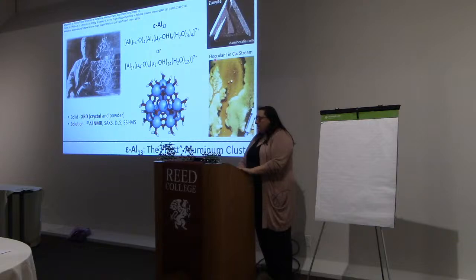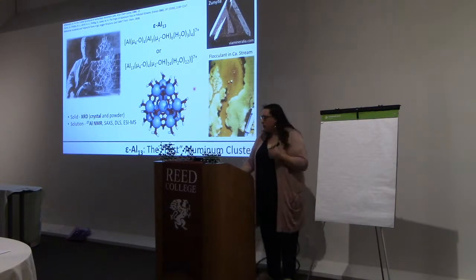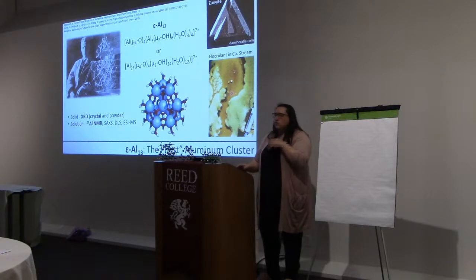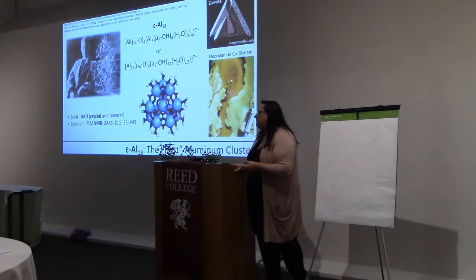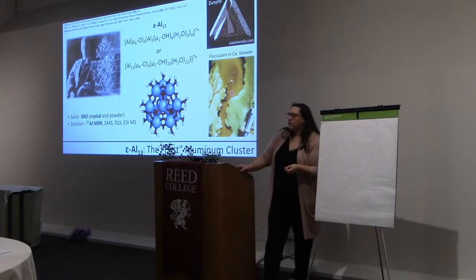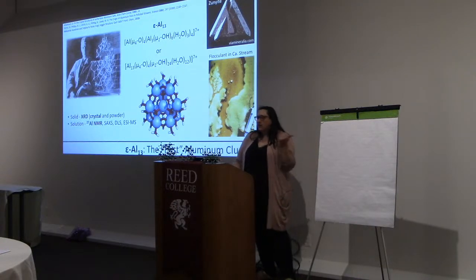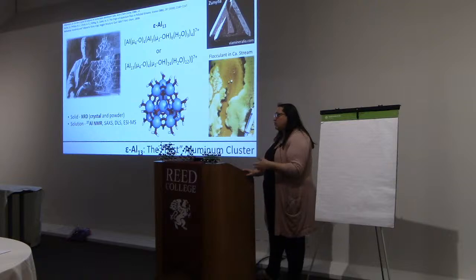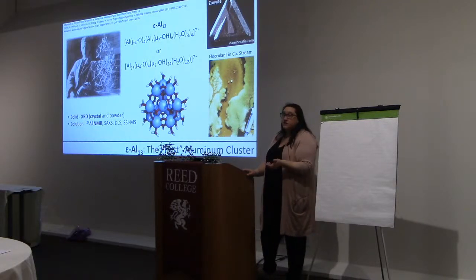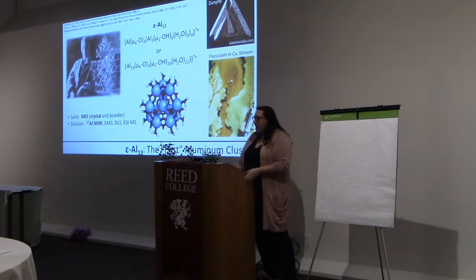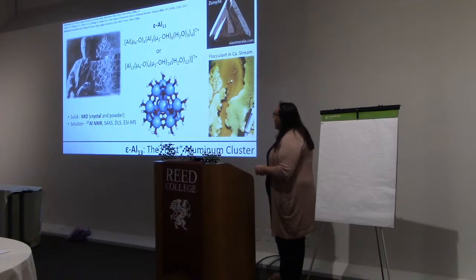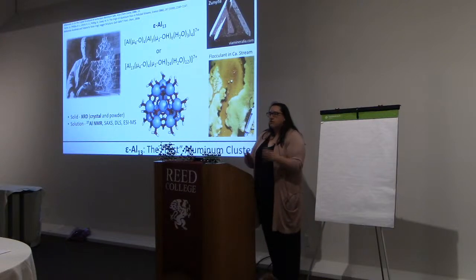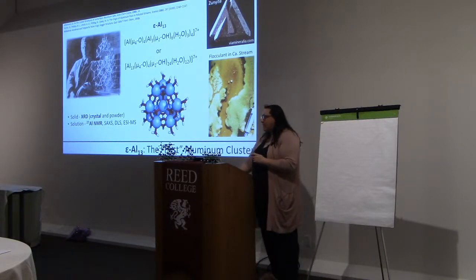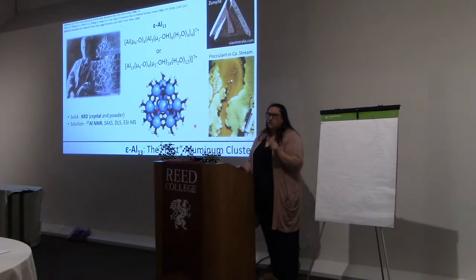So in 2002, this cluster was found in nature for the first time. They took some flocculants from a stream in California and tested these with solid state NMR, and then they dissolved it into solution and were able to see that this cluster is just naturally forming in this stream. And then there's this beautiful crystalline mineral here called zunyite. And naturally in that crystal structure, there are subunits that are very similar to our epsilon aluminum 13.